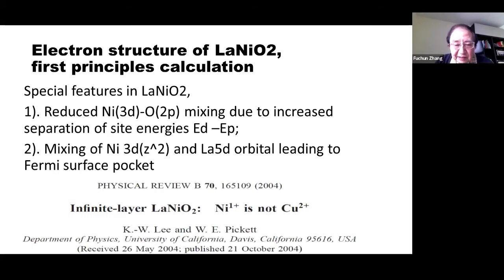Quite 16 years ago, there was a first principle calculation paper by Warren Pickett. At the time, they calculated the electronic structure for lanthanum nickel O2, which is believed to be similar to neodymium nickel O2. They found two things. One is reduced nickel 3d oxygen 2p mixing, due to the increased separation of the site energies, ED minus EP. That makes this Heisenberg exchange coupling J much smaller.